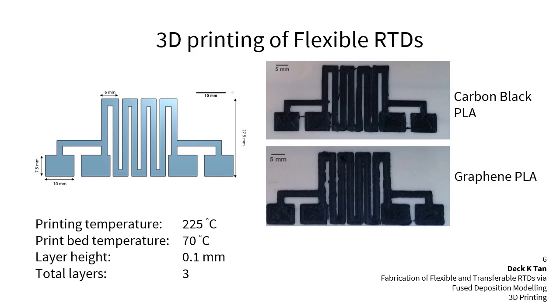These sensors were printed on flexible mylar substrate, and the printing temperatures were shown here, where the printing temperature was set at 225 degrees Celsius and the print bed temperature was set at 70 degrees Celsius to allow a slower cooling of the extruded filament. Each layer height was set at 0.1 millimeters and 3 total layers were printed.